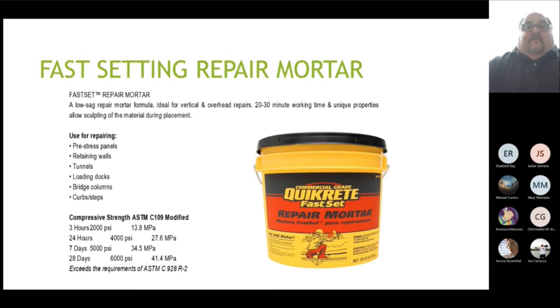So the next product we have, talking about limitations and things like that, this one has a much better ability to do more things than even the vinyl concrete patch. It's called Fast Set Repair Mortar, and it's our commercial grade line. It's a fast setting repair product that can go vertical and overhead. It usually sets in about 20 to 30 minutes. You can go 2 inches thick with this product. You can extend it with aggregate if you need to.